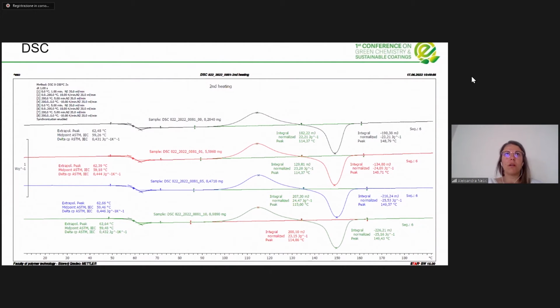We are now waiting for the results from the crystallization experiments from XRD. We want to check the crystallization rate of the samples, because we assume that this crystallization is one part from the PLA, and another part might come from the pseudocrystals that are formed around the molecules with the shorter chain lengths. So they have the role as nucleating agents for PLA. So it might happen, but we are still trying to find out why the thermal properties are the same actually